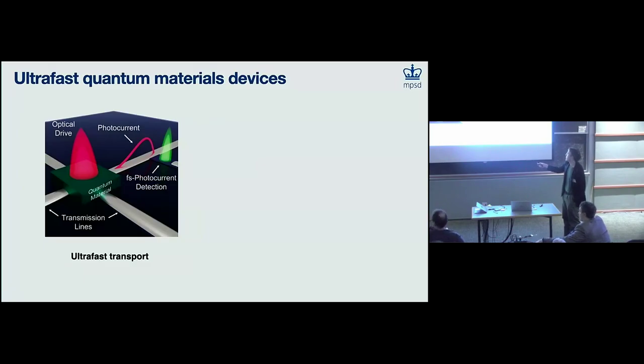And then we can run source-drain biases. If it's a 2D material, we can gate the Fermi level. And then we photoexcite the material, and you can change the wavelength, polarization, and whatnot. And then we look at the photocurrent signals that leave out the different ports of the device, which we then detect downstream using a different photoconductive switch. So we're essentially replacing the generation switch with the quantum material.